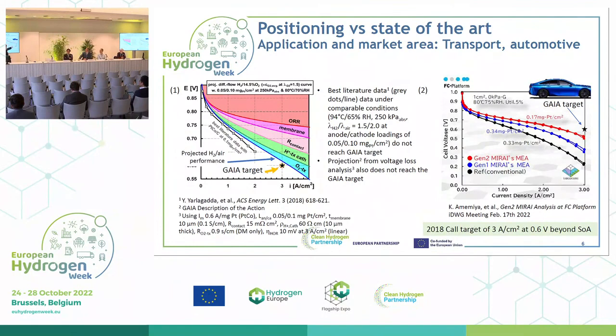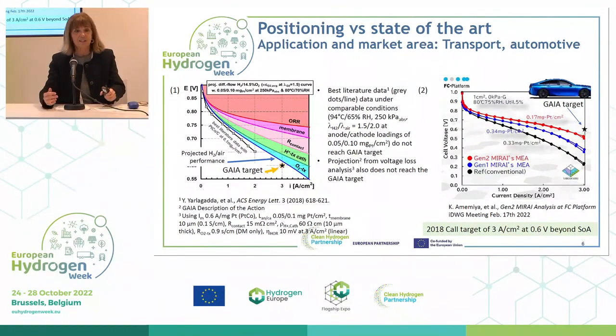So this is showing polarization curves for the first generation of Mirai, the second generation of Mirai, and once again the GAIA target. This is just to show you that it's exceedingly difficult to achieve that target, and that the 2018 call target at 3 amps per square centimetre at 0.6 was definitely beyond state of the art.